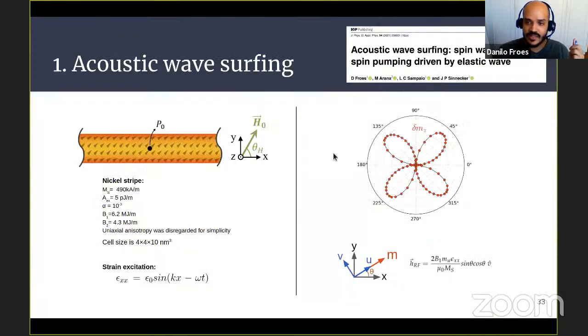For the acoustic wave surfing, we published it at the beginning of this year in Journal of Physics D. Basically, we took a nickel stripe that is 1 micrometer wide and very long, 10 micrometers long. We disregarded the uniaxial anisotropy for simplicity. We put in the magnetoelastic coupling coefficient and did a strain excitation like this, with a specific k and specific omega, with an acoustic velocity of 4,000 meters per second, a typical piezoelectric material sound velocity.